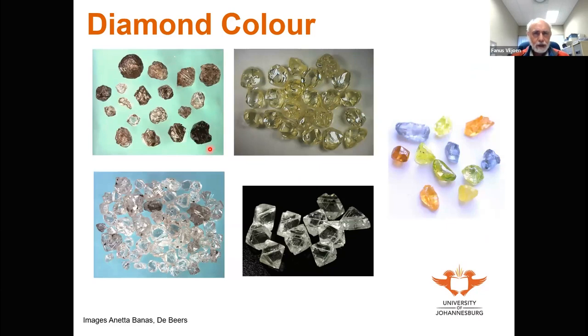Some examples here are black diamonds or gray diamonds, as you can see, some examples of colorless diamonds, yellow diamonds over here due to high nitrogen contents, and some examples here of blue diamonds, low nitrogen content, along with boron contained in the crystal lattice. Some stones here that are essentially variants of orange or brown, probably due to plastic deformation. And then this peculiar chameleon green color, as you can see here, due to a combination of nitrogen in a low aggregation state, possibly combined with plastic deformation in the mantle.